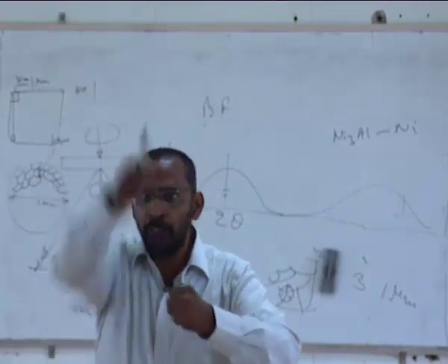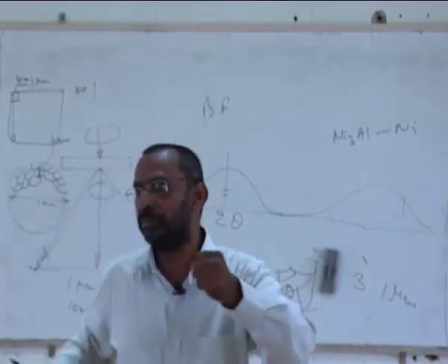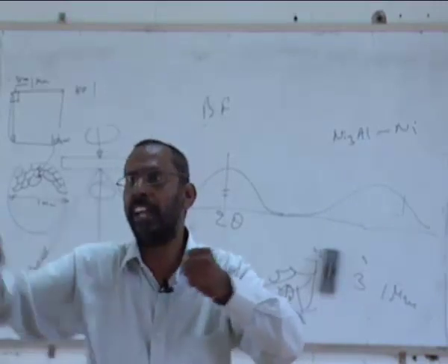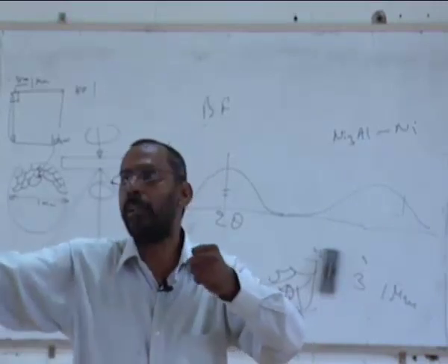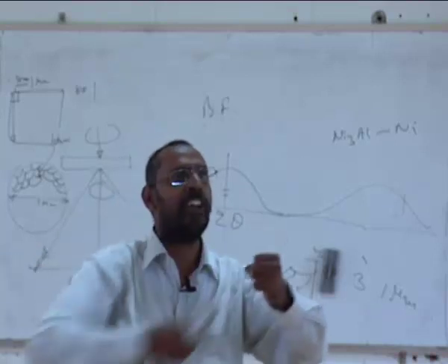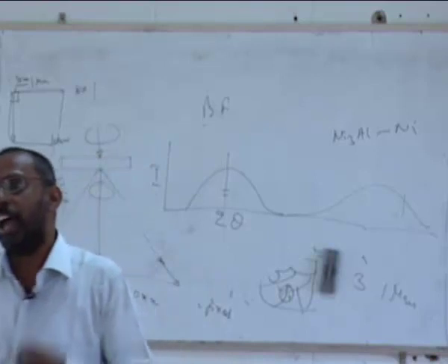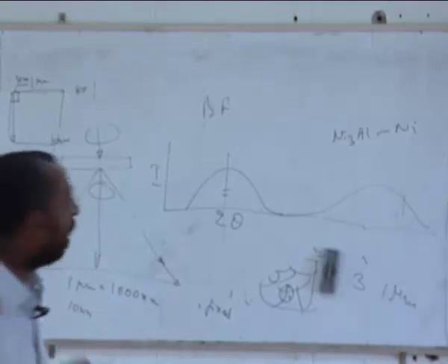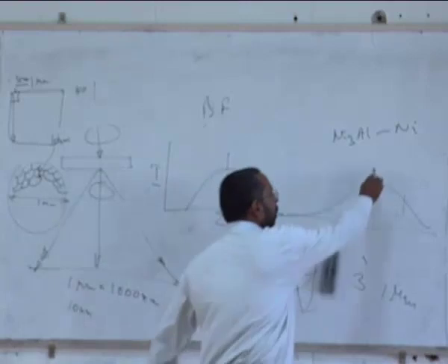So I can draw vectors from each of these atoms and find out the distance in each direction. What is the first atom that I am hitting? I can measure the distance and take the average of all these distances. I call it the average first nearest neighbor distance. And similarly, I can talk about the average second nearest neighbor distance. And those are the values that I get from these.